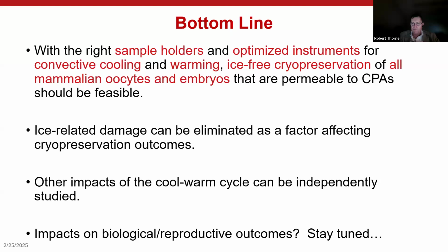So what changes when you have solutes, cryoprotectants around? Well, now your critical nucleus still has to be pure water. But you've got all of these cryoprotectant, all these solute molecules floating around. So the probability of your forming a cluster of the critical size that is just water and doesn't include any cryoprotectants, there's a distribution for that.